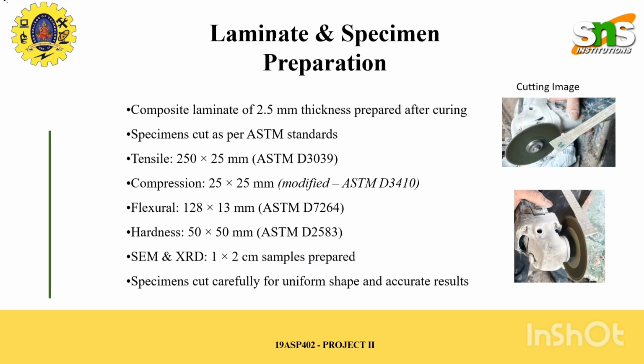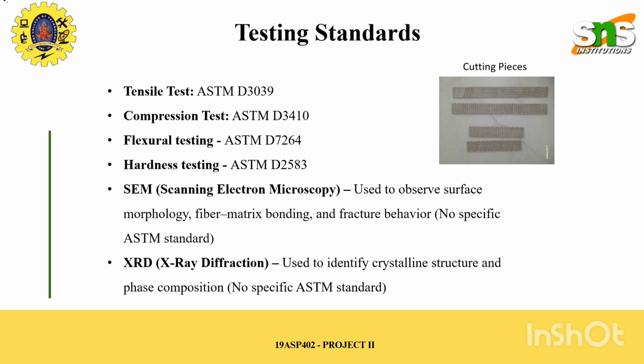After the curing process, the composite laminate of 2.5 mm thickness is obtained. The specimens are then carefully prepared according to ASTM standards for different mechanical tests. Tensile specimens are cut to dimensions of 250 by 25 mm, compression specimens to 25 by 25 mm, and flexural specimens to 128 by 13 mm. Hardness samples and small sections for SEM and XRD analysis are also prepared. Proper cutting ensures uniformity and accuracy in test results.